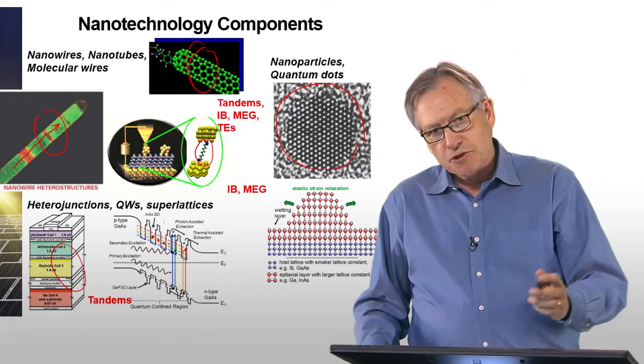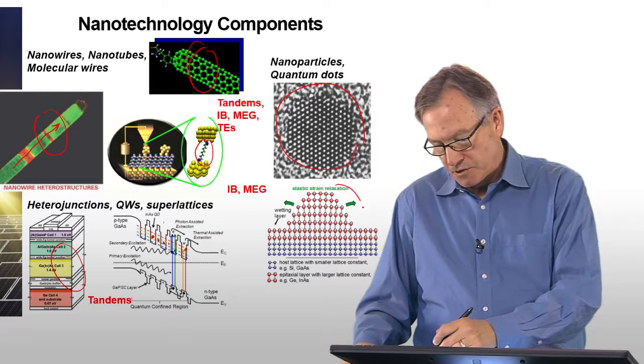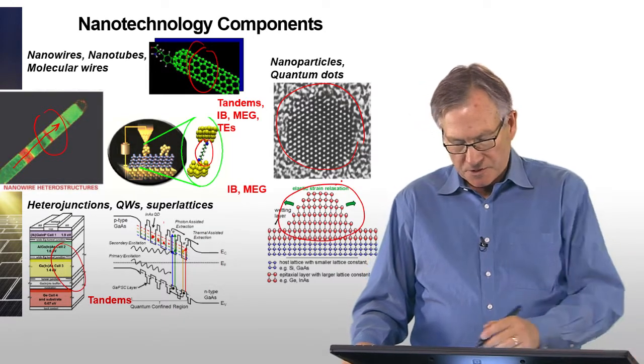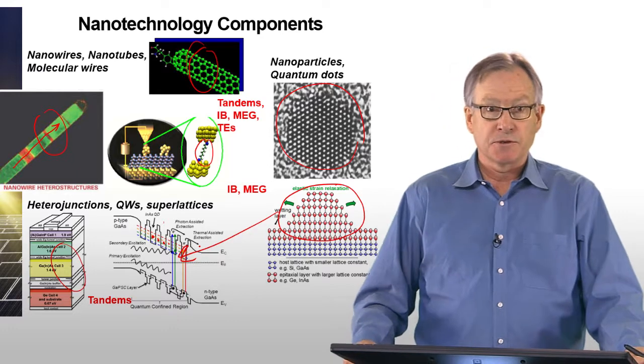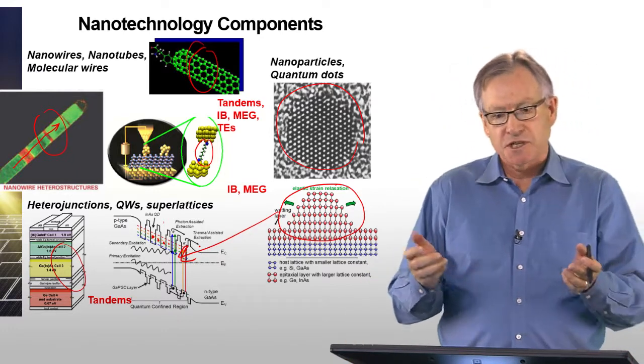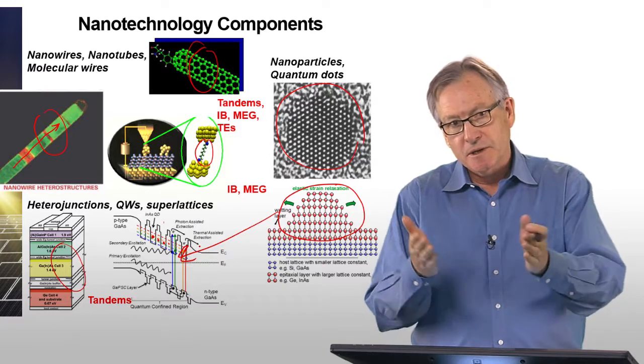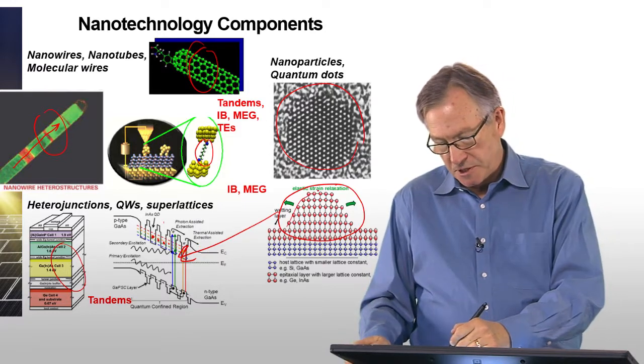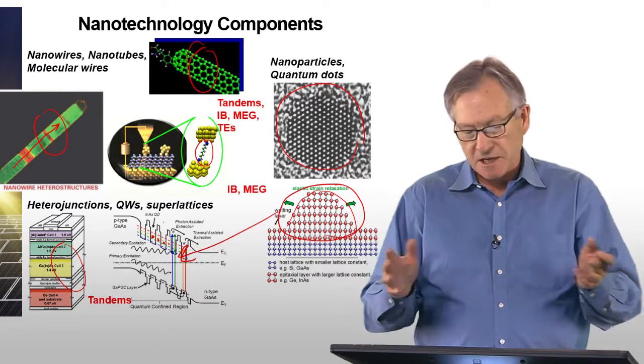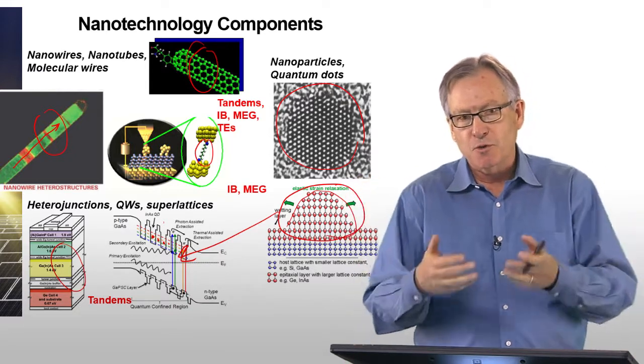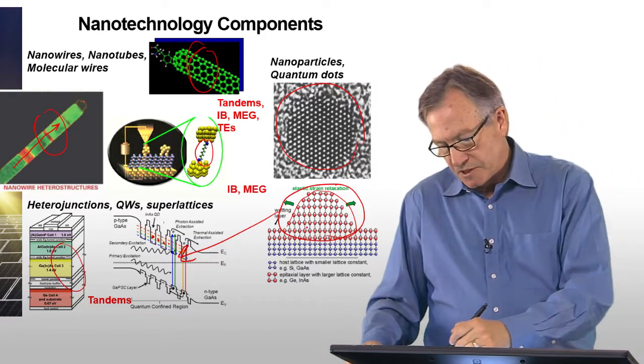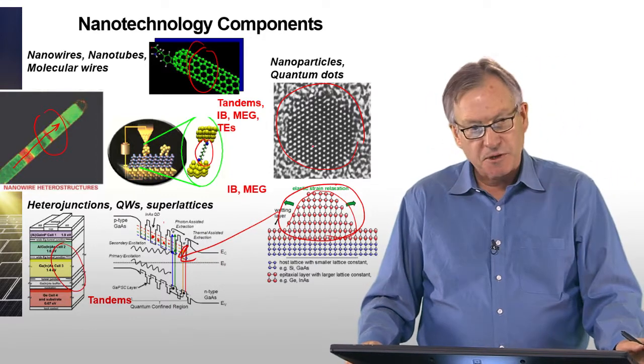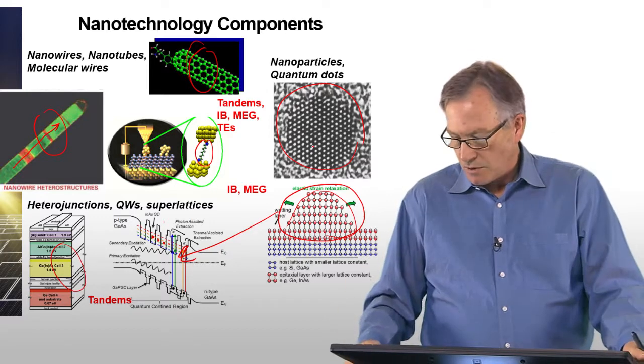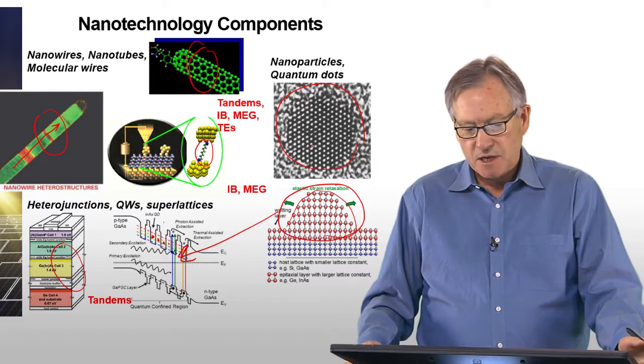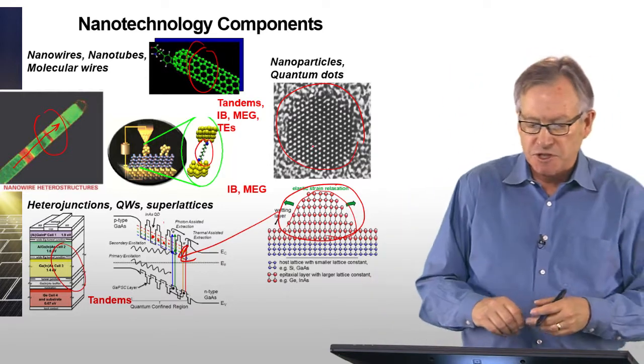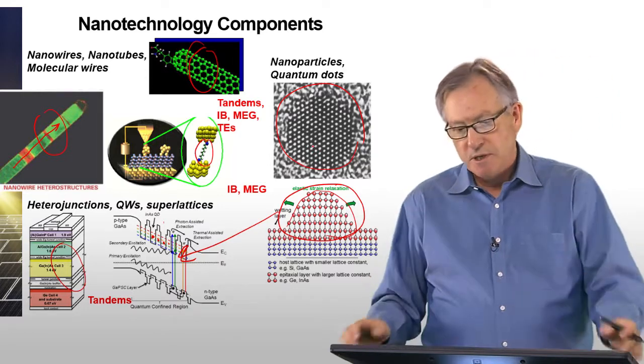So these can be synthesized in solution, or they can be grown, as shown down here, during epitaxial growth, the same process that's used to grow this, but if you grow it under high strain conditions, instead of the layers growing layer by layer, they clump up and form basically pyramids. And these pyramids are stable, and they actually form with a distribution that's fairly uniform around the crystal. And these pyramids then form quantum dots or nanoparticles that have basically zero-dimensional or molecular type of energy states. So these are sort of the tool bag of nanotechnology that we have available to us and what we try to utilize.